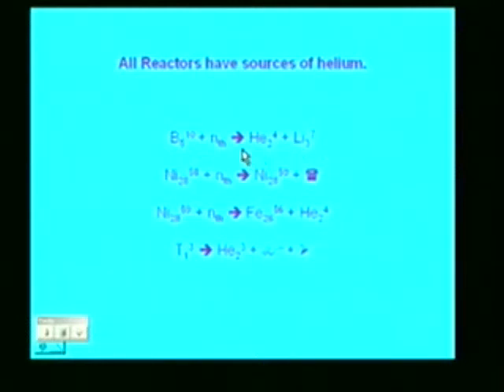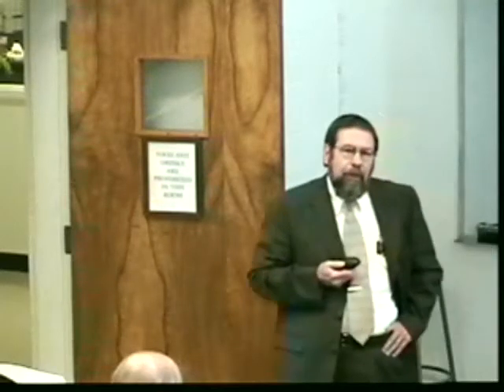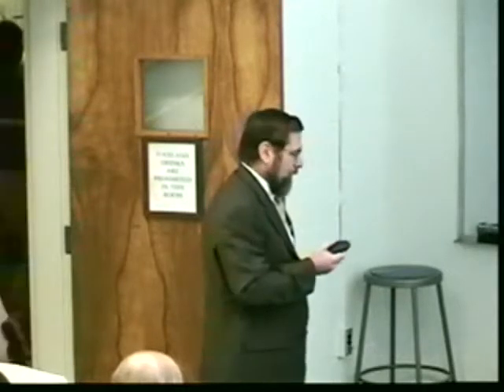And this can be important in LWRs, for example. We have stainless steel core components. Stainless steels typically have boron concentrations of 10 to 30 ppm. And 1 weight percent boron will ultimately burn to 1 atomic percent helium. So we'll talk about that a little bit later, but small concentrations of boron can lead to trouble.